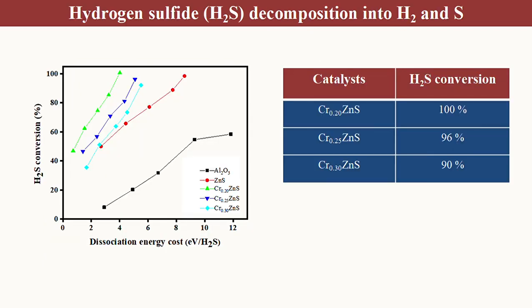Hydrogen sulfide decomposition into hydrogen and sulfur. The catalytic performance of the chromium zinc sulfide catalyst samples was evaluated for hydrogen production under non-thermal plasma treatment. The catalytic performance of undoped zinc sulfide and aluminum oxide as a support material was also presented.